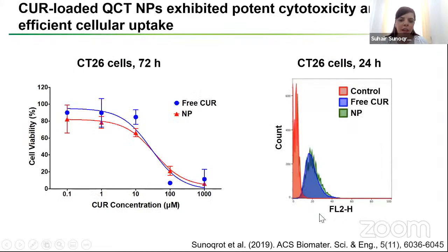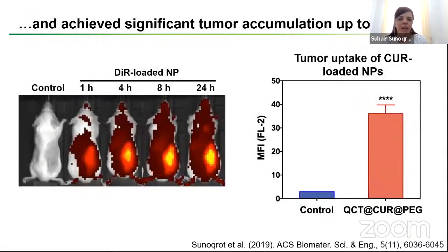So we took them further and we characterized them. For example, we tested the cytotoxicity in vitro, and they were equally potent like the free drug. The cellular uptake was also similar to the free drug. And we took it a step further, tested their accumulation in vivo in a tumor xenograft model. In this case, we loaded them with DIR as a near infrared dye and performed in vivo imaging up to 24 hours. And we could see that they could accumulate in the tumor. So they work for passive targeting.